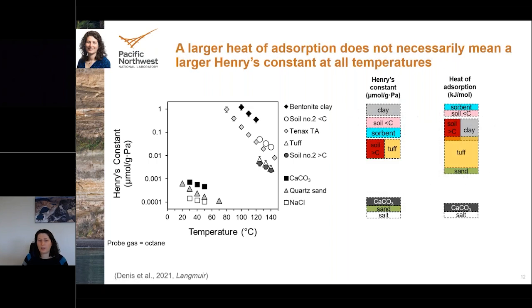And then on this slide, I've stacked up the results for the Henry's constant and for the heat absorption for the same materials. So that's what I'm showing on the right. And then this is still just the same Henry's constant plot on the left. And then you still see the two main groups with more absorptive materials and less absorptive. But although the differentiation is similar in regards to the two main groups, a larger heat of adsorption doesn't necessarily mean that you're going to have a greater Henry's constant value. So it's important to make both measurements and get to understand your materials in this context.